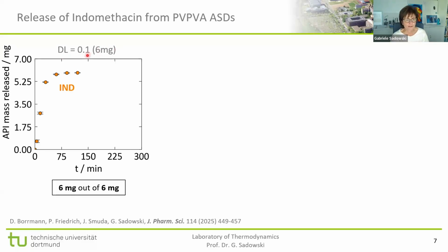For the drug load 0.1, we see that this was the one where we had a release of almost 100%, meaning that after a certain time, all of this 6 milligram is released into the water, into the aqueous system. So that means we had a release of 6 milligrams out of the 6 milligrams we had in the sample, which means everything was released. So now what we have seen on the previous slide is that increasing drug load means that we have a decreasing release in percent. So one could think, okay, let's simply increase the drug load, and if it's releasing worse, then we could maybe simply release the absolute amount.